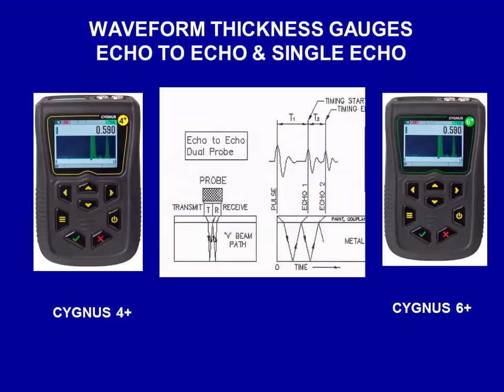You can ignore coatings with that, but you can only ignore coatings in the range of 40 mils, 50 mils. And I can show you that our gauges ignore coatings. They're 20 mils thick. 20 mils, 20 millimeters. Okay, no, mils. So it's only for really thin coatings, and they can paint more than once. Echo to echo won't work on them.